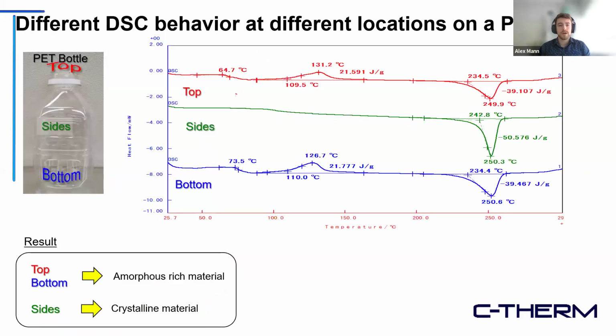So starting off with some examples, some polymers are crystalline by nature, but we can force them to be amorphous. What this means is that the polymer wants to have its molecules in a nice orderly crystalline fashion, but we can force them to be random or amorphous. We do this by melting the crystalline polymer, and then we quickly reduce its heat. So we quench it, and by doing that, there's not enough time for the molecules to get into a nice ordered structure. They freeze in a random orientation.